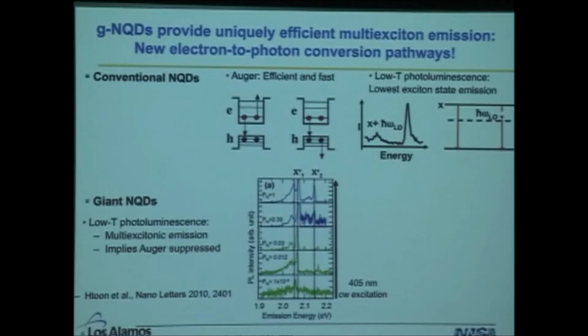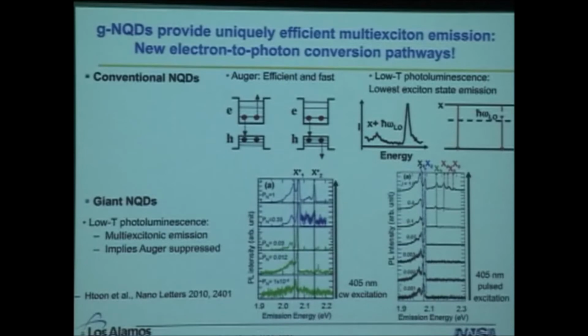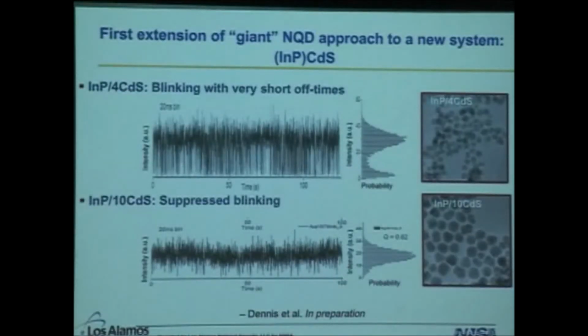In this case, I'm showing charged exciton and charged biexciton states. We also see much higher order multi-exciton emission, depending on whether we're pumping CW or pulsed. But anyway, clearly something new in terms of the fundamental photophysics is happening in these systems. And that's exciting. Now as a chemist, of course, we'd like to say that we just didn't get lucky. We'd like to be able to say that we can control this, we understand this well enough that we can go ahead and translate what we've learned from the cadmium selenide, cadmium sulfide system to another system.